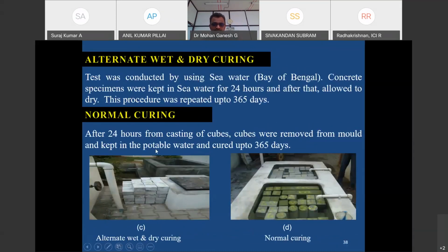Normal curing, you know very well. In the beginning itself, I said to you, we have done curing up to 365 days. The main reason for 365-day curing is that we have replaced the cement with 60% of fly ash. So for that only we have done the 365 days. And again, as I already said, durability is the most important one.